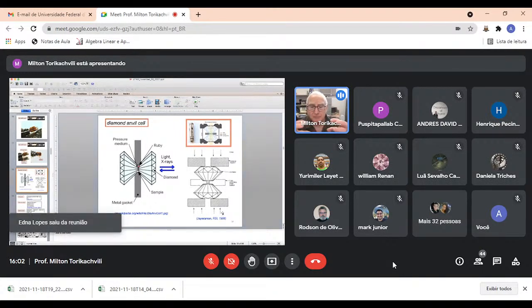So you basically prepare 2 diamonds with flat culet. A culet is the flat part. It's usually the pointy part of the diamond, right? The top here is the table, and this is the culet. But now you flatten the culet. The typical dimension of the culet is about 500 microns, or half a millimeter. Now, this is what happens. If you just push those 2 diamonds against each other, they will break very, very easily.